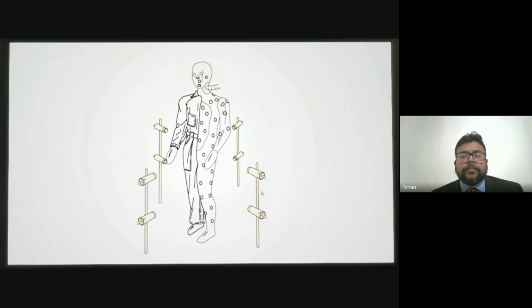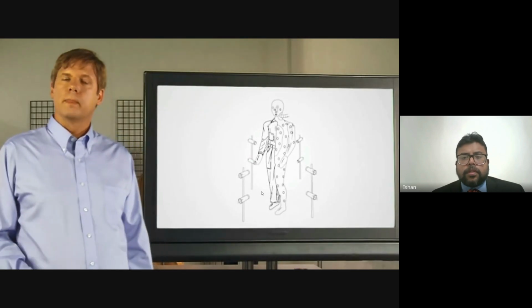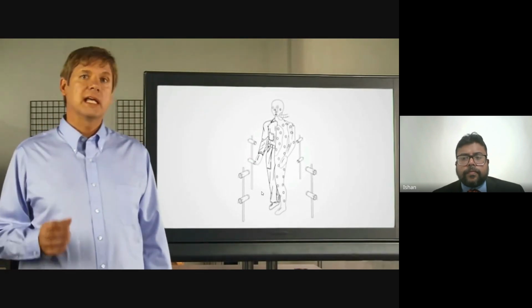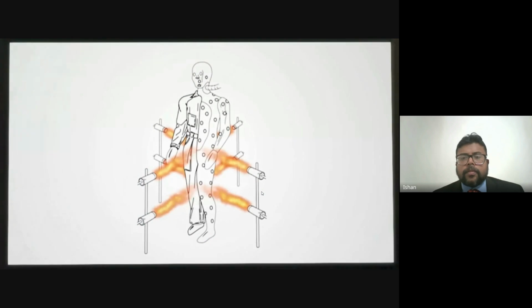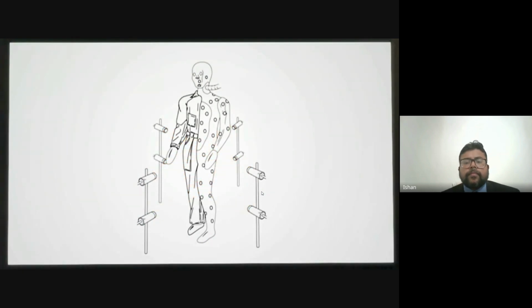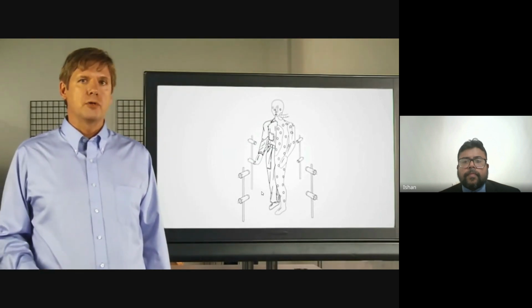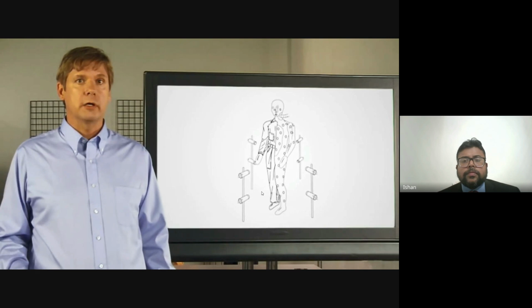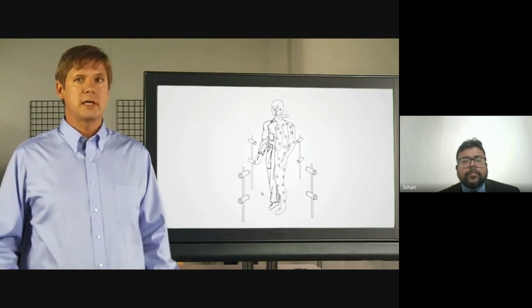In order to test a fabric, you need to create a coverall out of the material being tested and wash it once. The standard actually outlines the size and design of the coverall and how it is to be washed. You put this onto the mannequin over a set of 100% cotton t-shirt and briefs. So, you have the mannequin dressed, and then a simulated flash fire is initiated. The burners are lit and project flames onto the coverall for 3 seconds. During the fire exposure, the heat transmitted through the material is measured by those 100+ sensors.